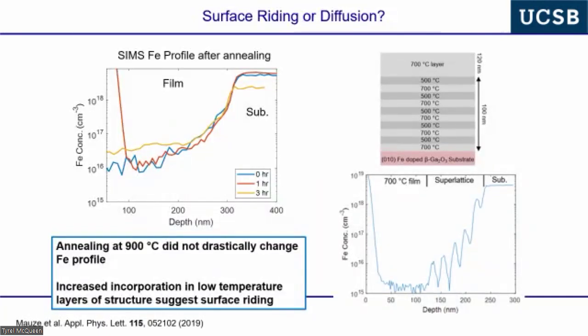But we had just completed around this time work on surface segregation in the material. And if you actually anneal a film on a substrate at much higher temperatures than the epitaxial growth temperatures, you actually don't find this profile changing at all. So this profile really can't be diffusion because if we anneal at temperatures a couple hundred degrees C hotter than the growth temperature, this level should be going up. This edge should be becoming less well-defined. So it's probably not diffusion.